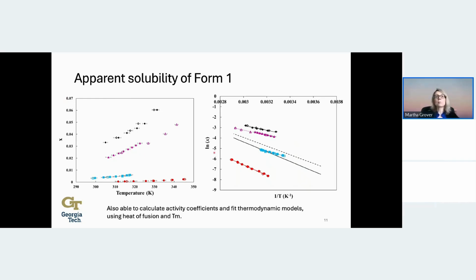And then we can plot that same data on a Van 't Hoff plot with the log of x versus 1 over temperature. So this is exactly the same data, but now plotted as a Van 't Hoff plot. And making some particular thermodynamic assumptions, one can derive a model in which these curves should be aligned. And so we fit a line, and actually the behavior is very consistent with being aligned. There's no reason that it would have to be aligned, but in fact it does have a Van 't Hoff type of curve.